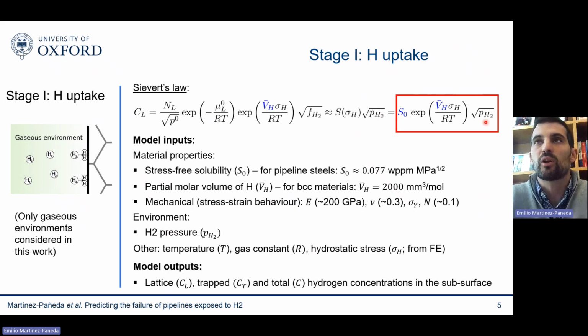You can see here that it's an exponential term. So this is going to magnify the impact of this hydrostatic stress. And as you can see, it has basically the gas constant, temperature, and the partial molar volume. So this we know, partial molar volume of hydrogen is this number here, and then all the other parameters we know. And the hydrostatic stress comes from a finite element simulation.